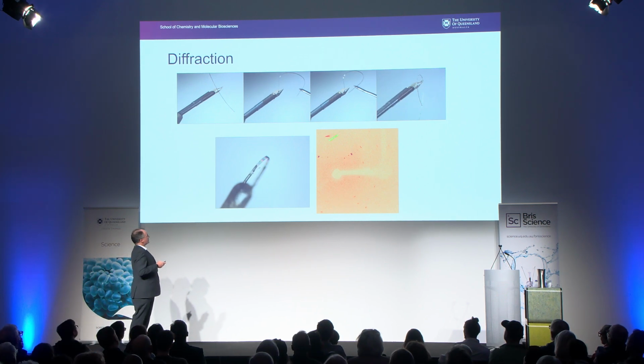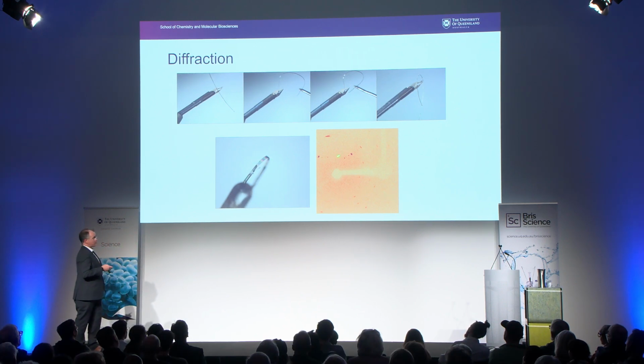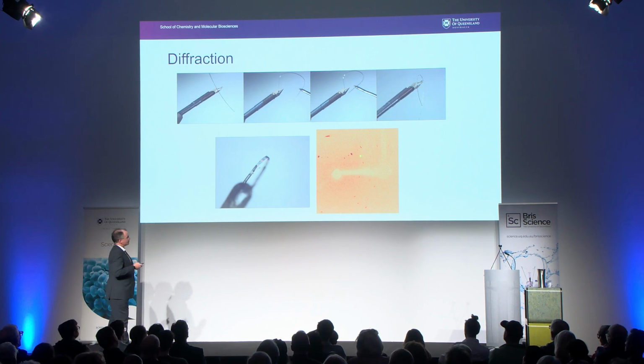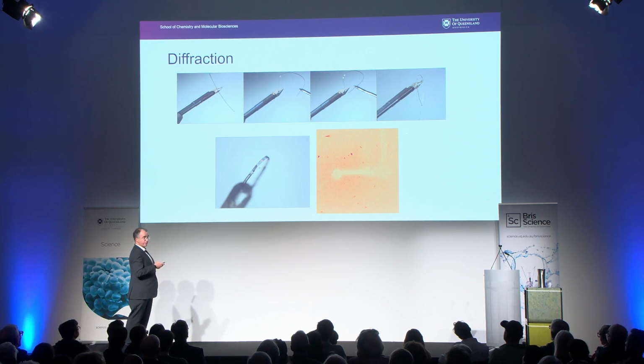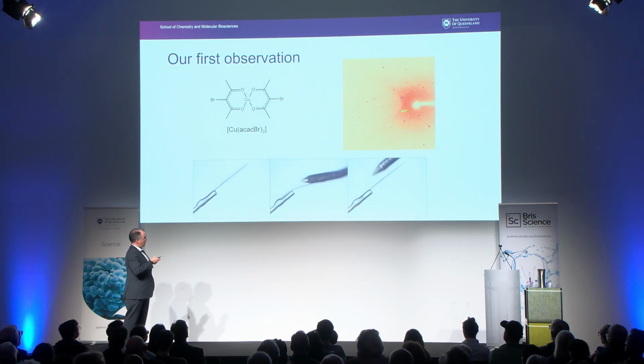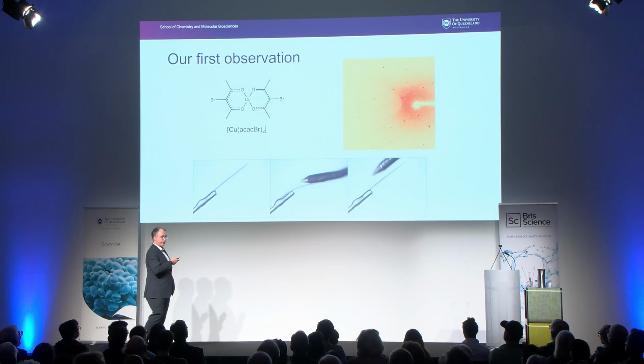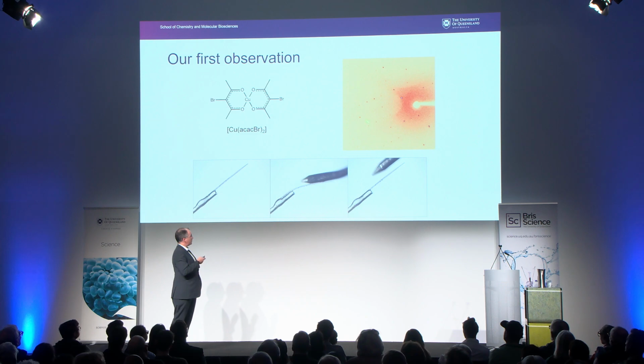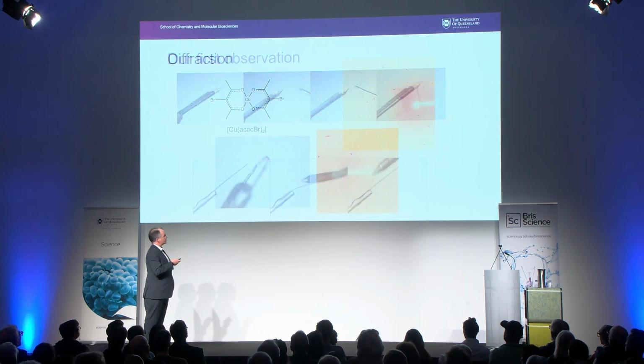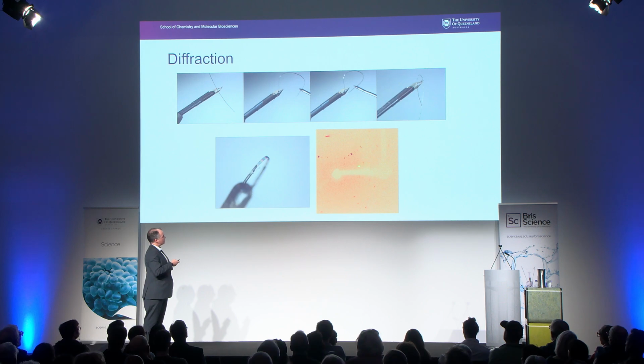What we did then was take one of these crystals tied in a loop, and we fired an X-ray beam at it. And this is what we see. We see a very broad diffraction pattern. So this is quite different to the nice, sharp, clean diffraction pattern that we were seeing here. Okay? It's very sharp, all of these spots are well resolved, but when we bend the crystal, we see now that the spots are still there, but they're much broader in shape.